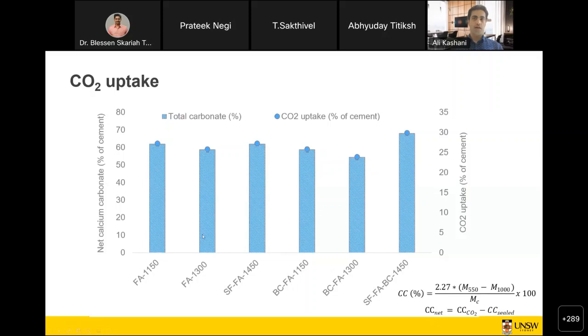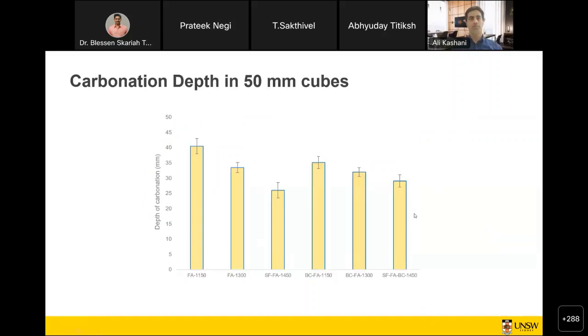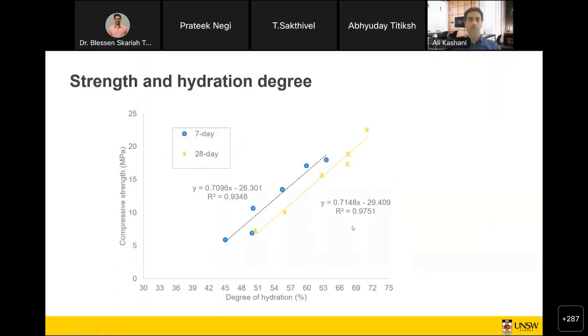And you can see up to 30% CO2 uptake can happen. This also depends on the mixture design and the density. As you can see, for example, in the sample with silica fume, fly ash, and biochar, biochar actually helps with better CO2 sequestration as an additive, and you can get higher CO2 uptake in those samples. And also the carbonation depths: you can see the effect of the density. The lower the density, the more porous the material gets, the higher the depth of carbonation inside the samples.